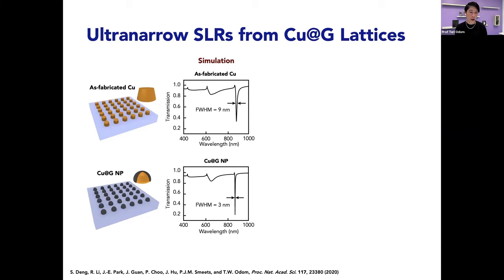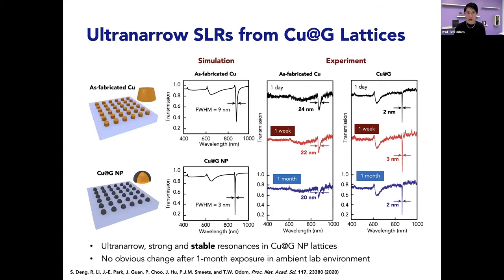So just to compare what the linear optical properties look like, these are calculated for copper and the copper that is coated with graphene. And you can see that the experiment matches quite nicely. But moreover, we have this really beautiful, sharp, and deep SLR from this hybrid system, this core-shell copper system. After a week, the full width at half max is still narrow, and after a month, it still remains narrow, even after being in ambient conditions.